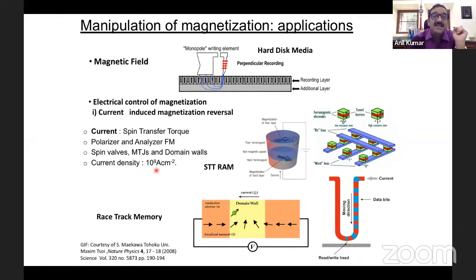And the current density that is required to switch this magnetization is 10 to the power 8 ampere per centimeter square, or 10 to the power 12 ampere per meter square. It's a huge current, right? So here comes the advantage of this dimension, centimeter square. So I can make the dimension of my system much smaller, so that the current density can be maintained, but the switching can happen, right?